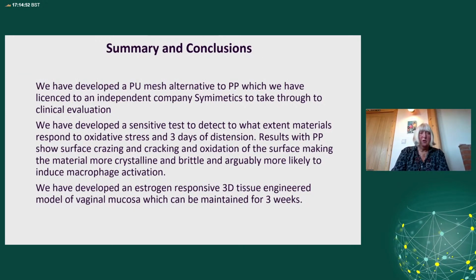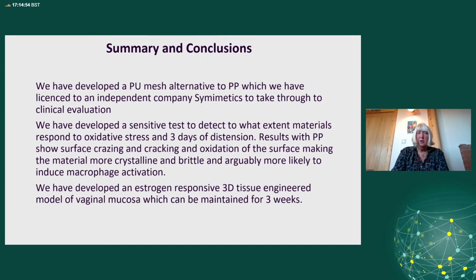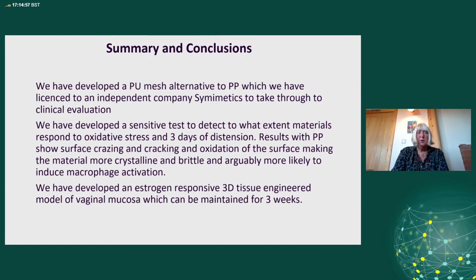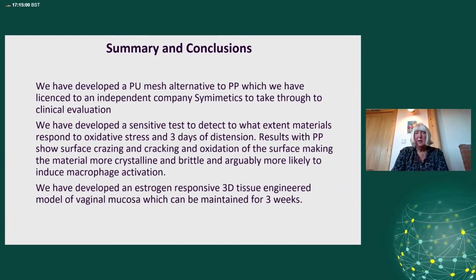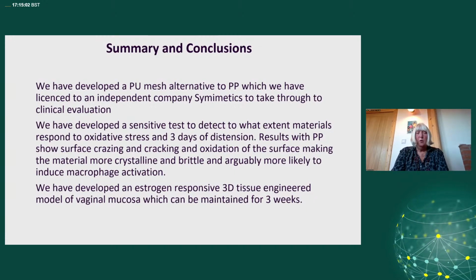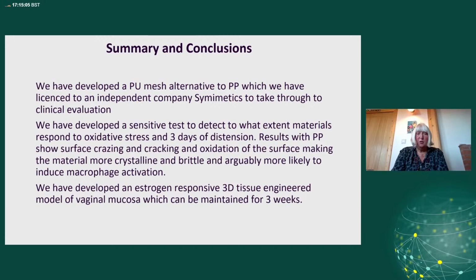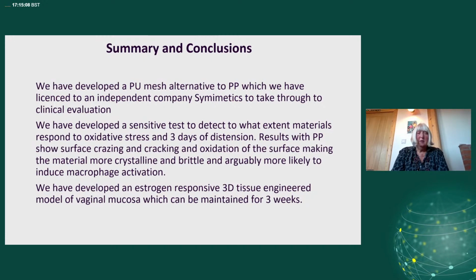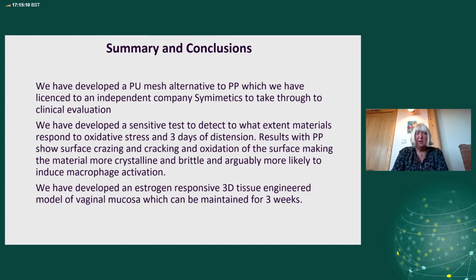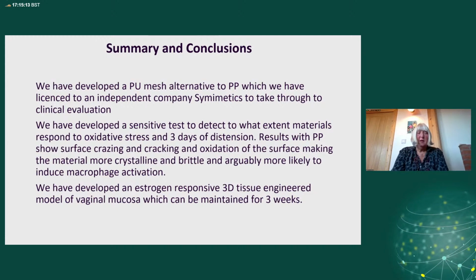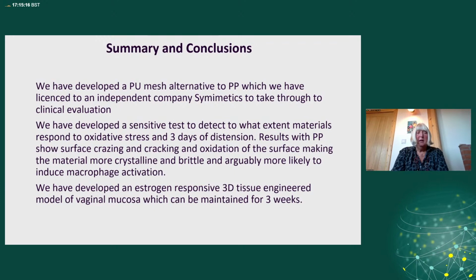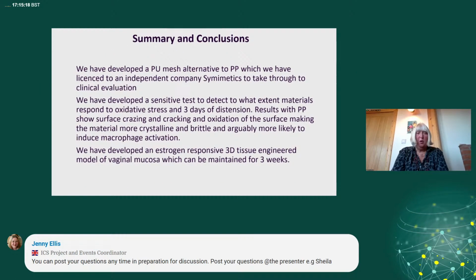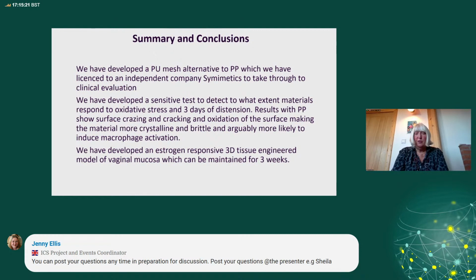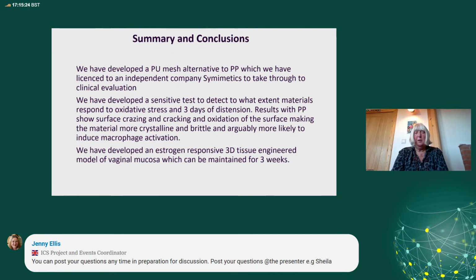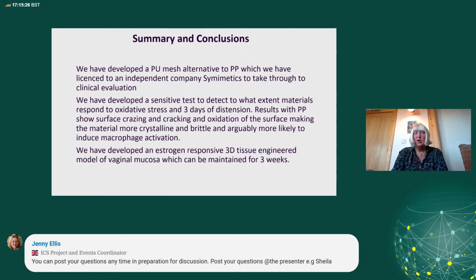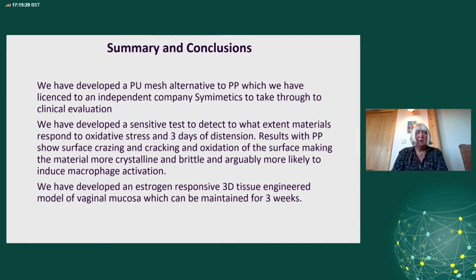So summary and conclusions. We've developed a PU mesh alternative to polypropylene, which we've licensed to an independent company, Symimetics, to take through to clinical evaluation. We've developed a sensitive test to detect to what extent polypropylene responds to oxidative stress and 3 days of distension. Results show surface crazing and cracking and oxidation of the surface polymer. This will make the material more crystalline and brittle, and arguably more likely to induce macrophage activation, but that's the area that we now need to go into.